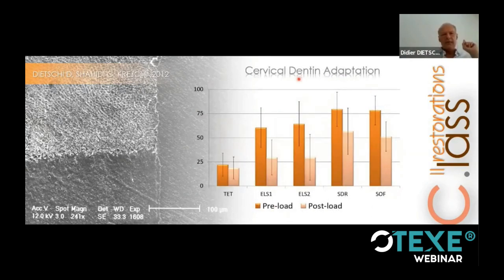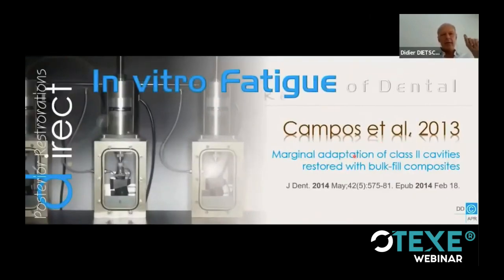If you look at the adaptation into dentin, we can confirm that if you use a regular composite with a bulk filling approach, it's not going to work. The SDR flow or SonicFill, which are among the well-known bulk filling materials, have non-significant difference in terms of dentin adaptation, but you see that you're basically close to 50% of excellent adaptation into dentin after loading. With this exact same machine, exact same protocol, we could get to 74 to 75% with the classical layering approach. It's another publication from our university, because there are not so many universities using those machines and those protocols.